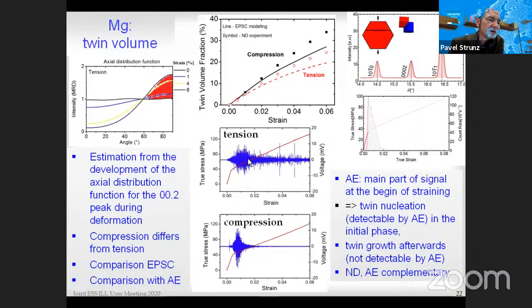straining, there is the major part of the acoustic emission signal, in both cases, compression and tension. It means that twin nucleation, which is detectable by acoustic emission, occurred mainly in the initial phase of the straining, while afterwards, the twin grows, this thickening of the twin phase. Twin growth occurred afterwards. And this is not detectable by acoustic emission, but it is detectable by neutron diffraction. So neutron diffraction and acoustic emission are complementary.